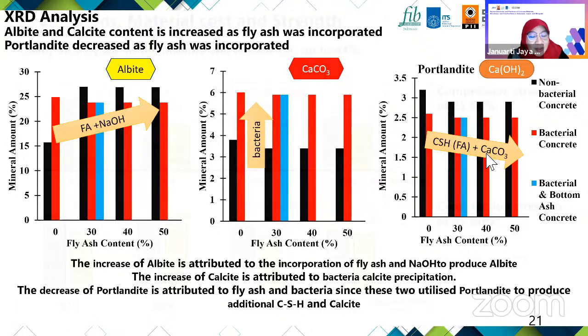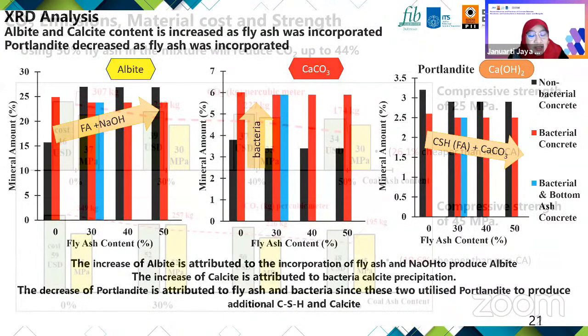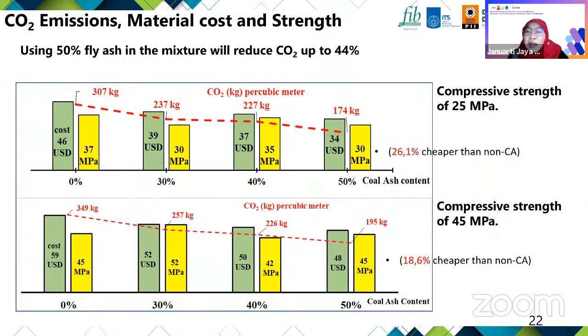And finally, we compare the result of normal strength and higher compressive strength. We found that there is a decrease of CO2 emissions by 44% for all specimens using 50% coal ash in the mixtures. And the cost of material is also reduced from 18 to 26%. It is a very good contribution to the concrete ready mix industry to get the carbon credit.